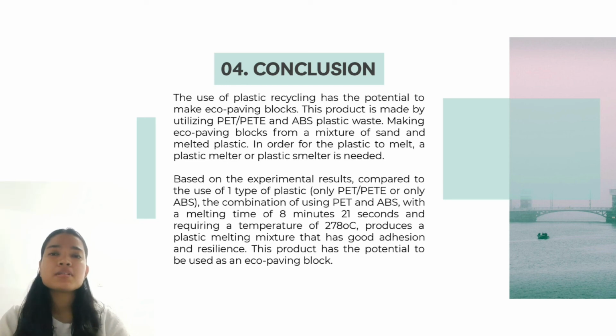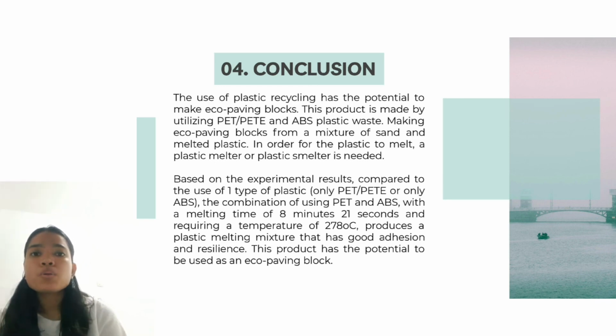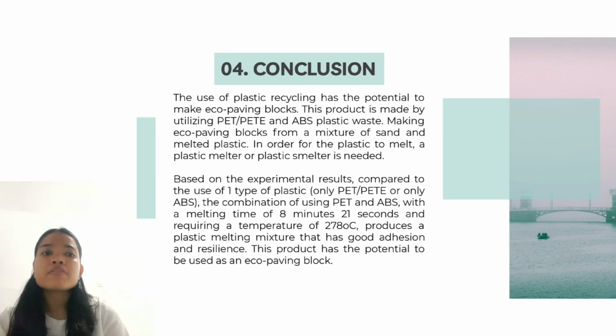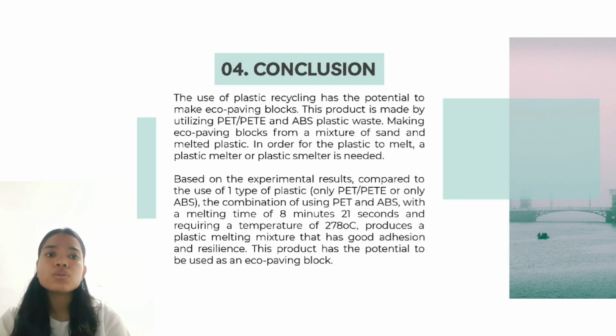Based on experimental results, compared to the use of one type of plastic, only PET or only ABS, the combination of using PET and ABS, with a melting time of 8 minutes 21 seconds and requiring a temperature of 278 Celsius, produces a plastic melting mixture that has good adhesion and resilience. This product has the potential to be used as an eco-paving block.